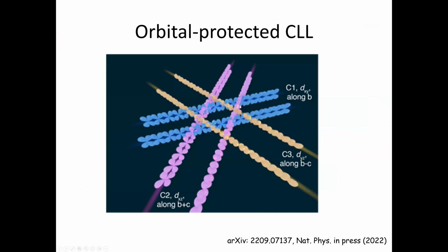But then if you take a look at the orbital character, you can see that the orbitals of the atoms form only three highways, like chains: dxy, dyz, and dxz. So these three chains are conductive. They share the octahedra, and they cross only at some points, and at this crossing point they have some interaction. This is pretty neat, because before this the crossed Luttinger liquid model was only attained by putting carbon nanotubes together, right? But that requires a lot of effort, and it doesn't form a uniform large crystal that we can study.